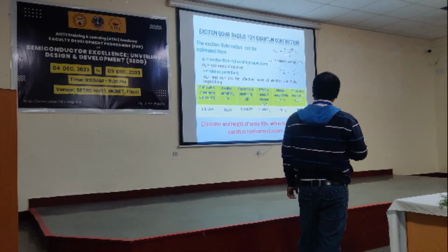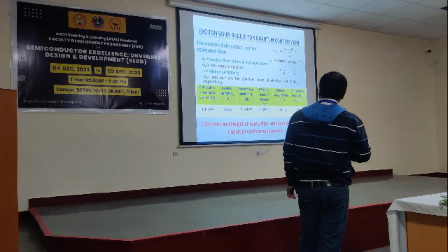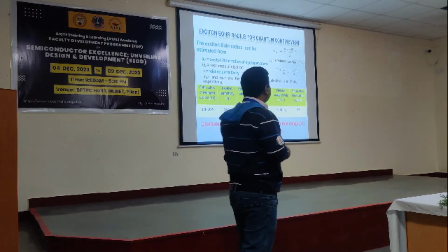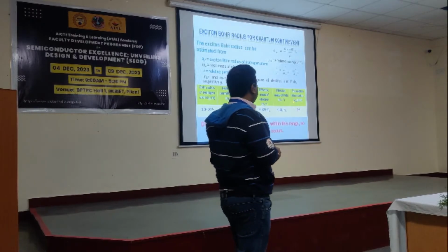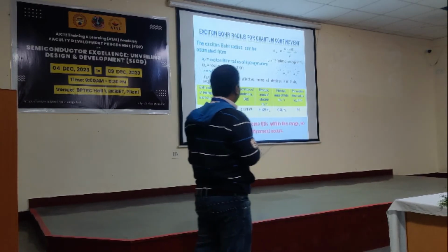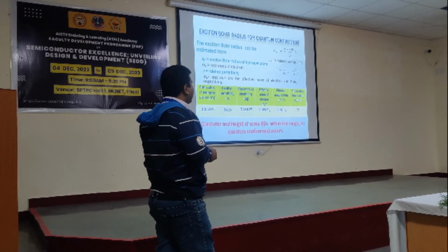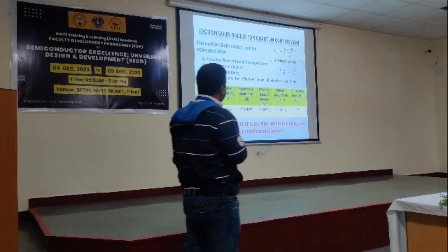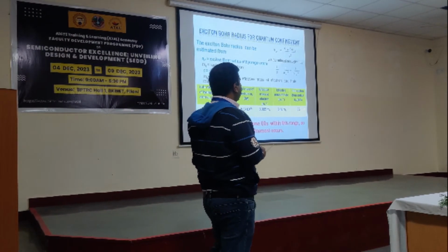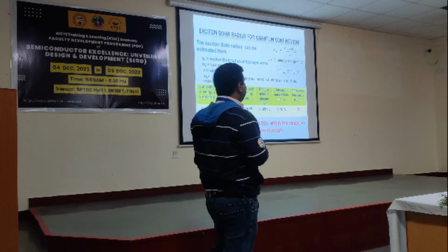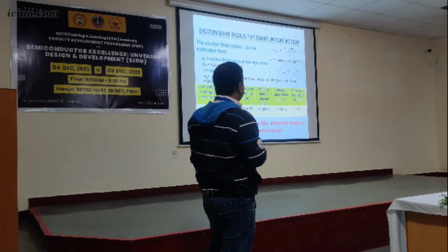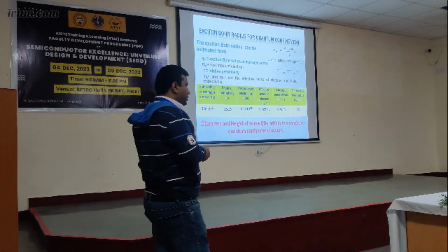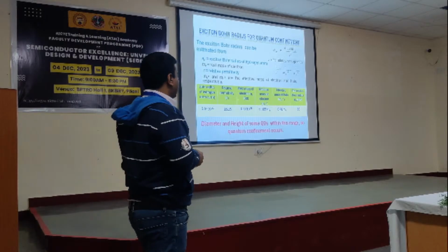All this is the formula. I have put all the values there. If you determine the value, the excitonic Bohr radius of indium arsenide is 36 nanometer. From this value, you can conclude that the size of the particle should be at or below this. If the size of the indium arsenide particle is 36 nanometer or below, then the formation of the particle is nothing but the quantum regime.